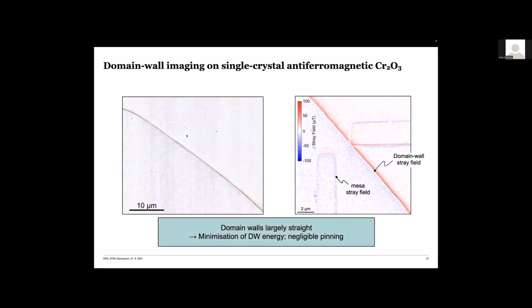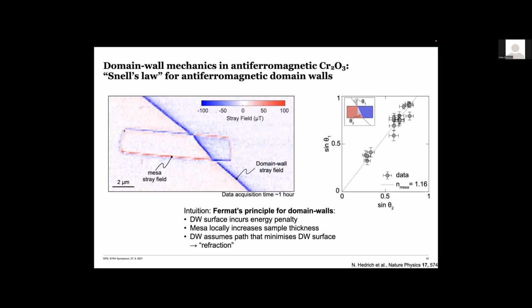All right. These domain walls, they were rather straight, in that sense, maybe boring, but also nice because it really showed that this is a rather pristine system where pinning of the domain wall is negligible. However, something interesting happened, and here I really just want to show this, and then I'll wrap up. Something interesting happened when these domain walls actually crossed the mesa structures, and that's something I show you here. So here's a zoom in into one of these mesas, with the domain wall going across, and you see that there is a behavior of this domain wall trajectory that really looks like refraction in optics. So obviously, the mesa is able to deflect the position of this domain wall.